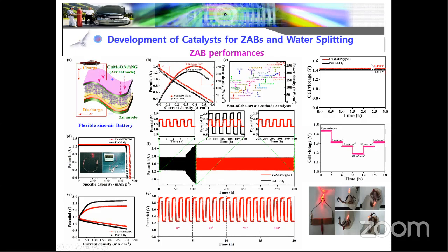Our catalyst also has a higher open circuit voltage (OCV) compared to the conventional couples, and compared to the platinum ruthenium material, it achieves a higher specific capacity. From the specific capacity, we also calculated that the energy density is higher, and the stability as well. You can see the previous catalyst using ruthenium and iridium lasted almost more than 112 hours, I think. In the case of our catalyst, it is stable up to 400 hours.